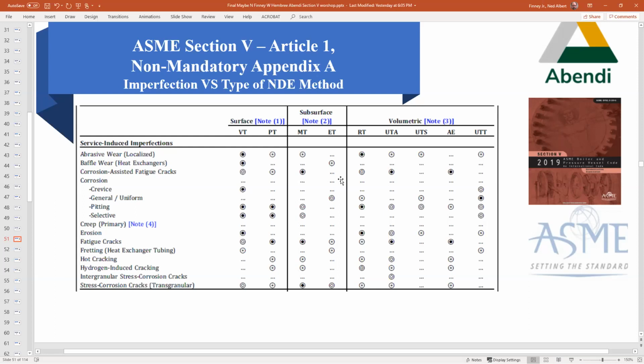This is what we had found for the different types of flaws. And rather than go down and read them for the sake of time, we just wanted to point these out to you so that when you look at this later, you can see, okay, here's creep damage, and there's a note to creep. But if you go right straight across the surface, you don't really see that much, and you've got a special note that really indicates that.